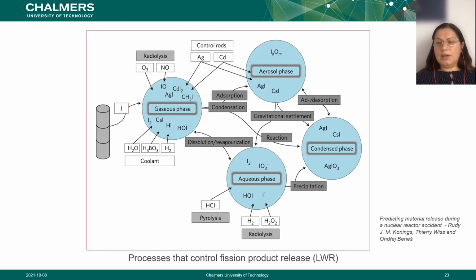So when you think about ejection of the cladding and all this, and we talked that the volatiles are coming out, here we have an example, only iodine. And from the iodine, you can see how much chemistry can happen only because you have radiolysis. This is in the case of water. You have radiolysis, you have from control rods some interactions with silver or cadmium, and then you form different chemical compounds which can or cannot dissolve in the water. If they're not dissolving in the water, you see that you have the dissolution here, then you might have some precipitates. Like here, you can have precipitation, you can have absorption and desorption, so this can go back and forth.